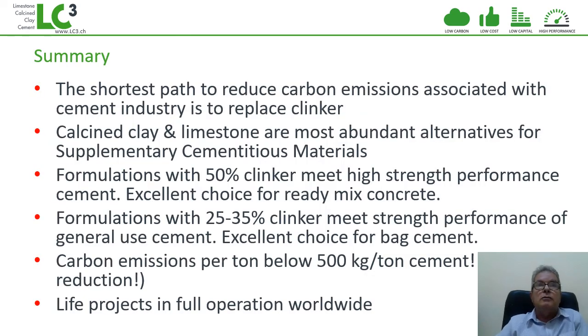With this, I can come to the conclusion of my presentation, meaning that there's an urgency of reducing carbon emissions in the cement industry. Calcined clays and limestone as supplementary cementitious materials are widely abundant, and combined with clinker, they can provide a cement that can match the properties of pure cements with very little clinker content. We have different formulations, and the important thing is that by using this cement, we're able to go below the barrier of 500 kilograms of CO2 per ton. And this is something that right now is going into real life projects.